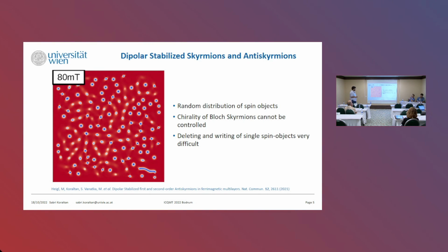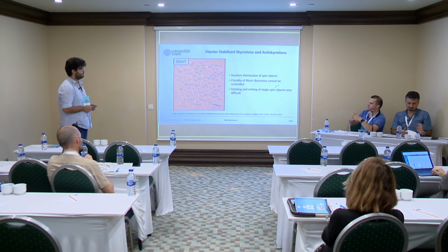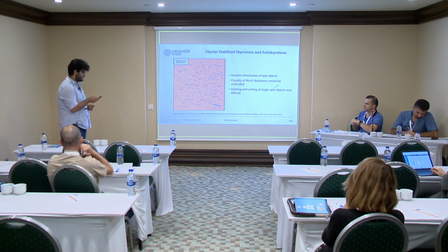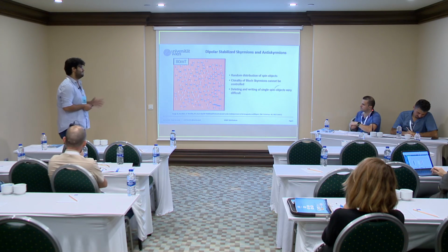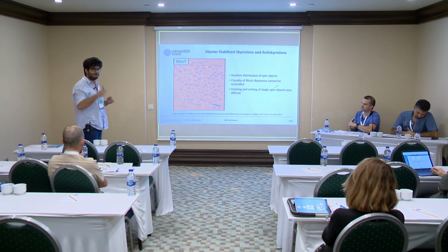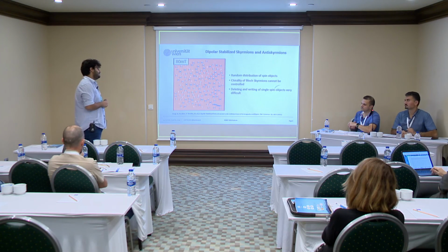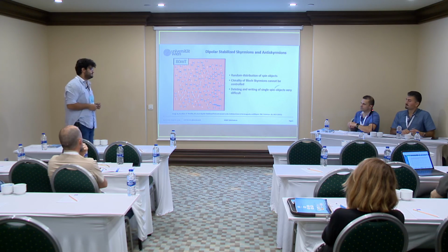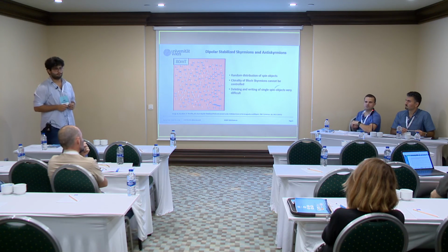Okay, so there would be some energy barrier to annihilate the skyrmion itself. Exactly. We also calculated the energy barriers, and they are also very high. But again, this is the problem. If you calculate energy barriers using micromagnetic simulations the way we do, it's inaccurate, because you usually have to go over Bloch points, and then you cannot describe them micromagnetically because you have an antiparallel lattice. Okay.